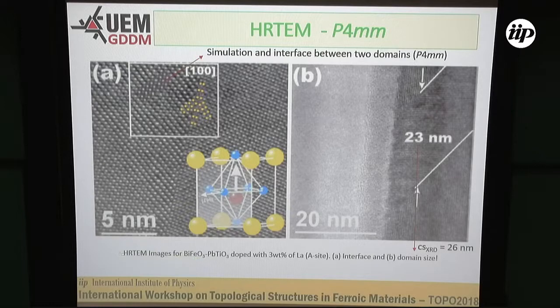We use high-resolution transmission electron microscopy to see this interface, which is indicated here, and to measure the distance between these interfaces. This distance is almost 23 nanometers, and the crystallite size, by using the Scherrer equation, we found to be 26 nanometers. In this case, the agreement is very good. This is a crystallite size that was measured by X-ray diffraction. It's very close to this domain size, now we can call it domain size, measured by high-resolution transmission electron microscopy.